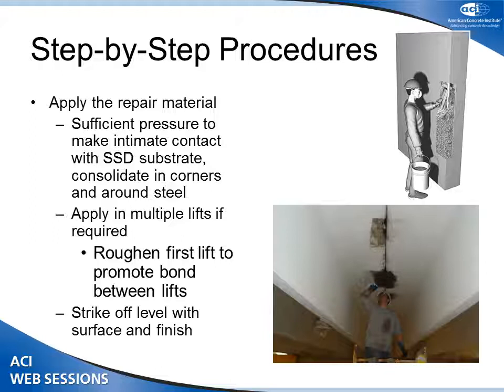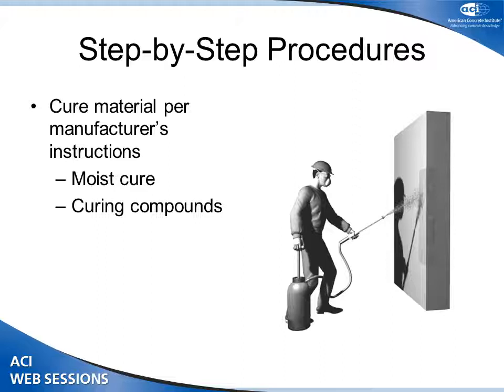And if the repair depth exceeds the limitations of the thickness of the material that can be achieved in one lift, you may need to do multiple lifts of material. So in that case, you'll do the initial lift. You'll roughen the first lift of material to provide a roughened surface for the subsequent lift to bond to, to achieve your final thickness. Then you're going to strike off and finish with trowels or floats. And then one step which is commonly omitted but is very important is the curing process. All these materials are Portland cement-based materials, so they need to be cured according to the manufacturer's instructions. Moist cure or curing compounds are commonly used.